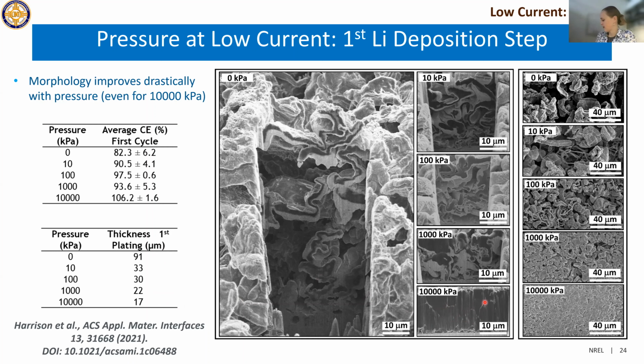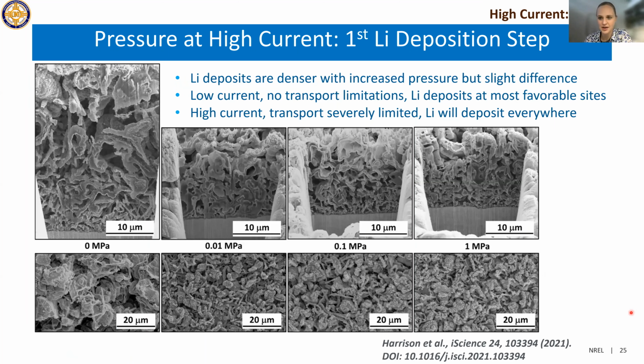So how that changes at high current was quite interesting, because we expected to see a significant difference with pressure for a high current. Previously we were at 0.5 milliamps per centimeter squared. This is at 4 milliamps per centimeter squared. Now you're seeing almost identical lithium morphology. The height of the deposits did change with the difference in pressure, but the lithium grains are still very thin, small, and more filament type of structure. To me, it looks a bit like spaghetti because it's all mixed together